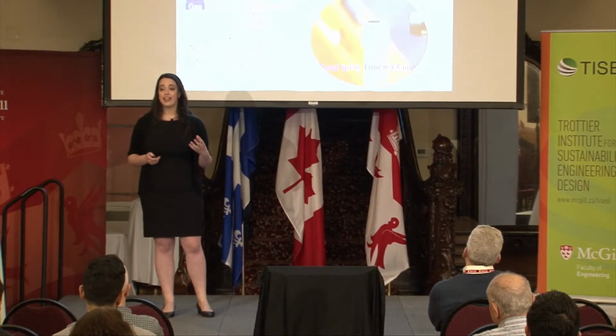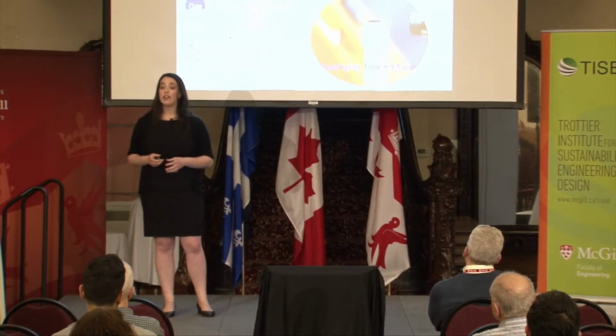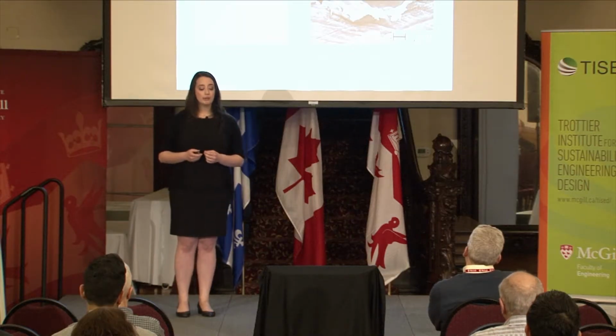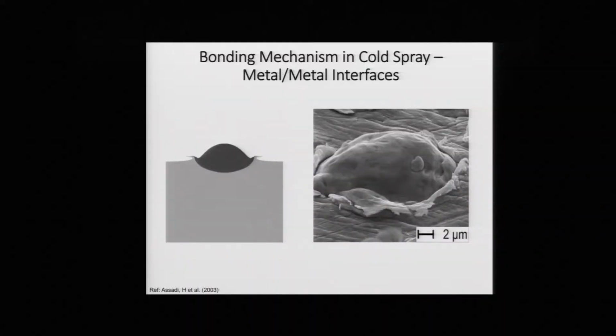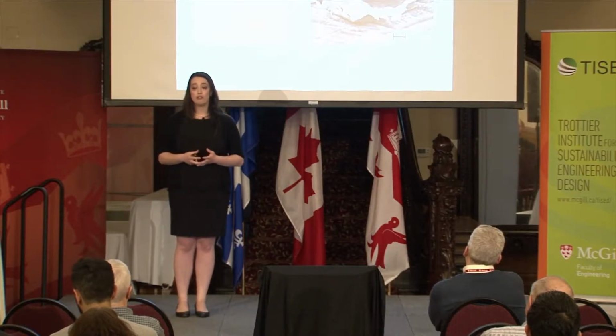But how do these particles get deposited? I mentioned, in order to get that 100% deposition, you need to understand the bonding mechanism. In metal-metal interfaces, the bonding mechanism is mainly through what we call plastic deformation. This plastic deformation is basically a term that we refer to as a permanent deformation of a material. And it's really that impact that induces the plastic deformation and results in bonding.